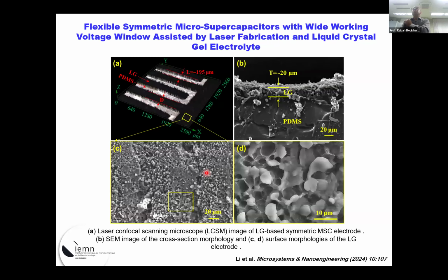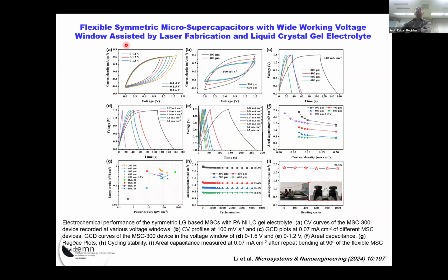So now we can see what's important, that the surface looks porous. This is very important, as I said previously, because then you can accommodate much more electrolyte, and then you can enhance the capacitance and the energy density. Okay. So you always find this typical, not ideal rectangular form, because you also have carbonyl groups on the laser-induced graphene, and those will contribute differently in a redox-type energy storage than just an EDLC type.